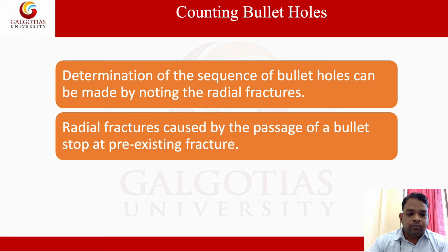Therefore, if a forensic scientist is examining the edge of a radial fracture, whichever side shows nearly perpendicular rib marks will be the unloaded side, that is the side away from the force that caused the break. Alternatively, if the forensic scientist is examining a tangential fracture, the side showing the nearly perpendicular rib marks will be the loaded side, that is the side from which the original breaking force was applied.